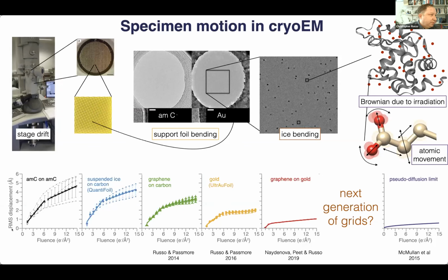This is the RMS displacement of a whole ensemble of particles like those ribosomes you saw on the first slide. And they moved anywhere from 0 to 5, 10, even more angstroms. And as we kept trying to develop better and better specimen supports, we reached on this idea that the foil was causing a lot of it. So we got down to about 2 angstroms, and this was back in 2014 and shown again in 2016. So this was good, but it wasn't quite there yet.